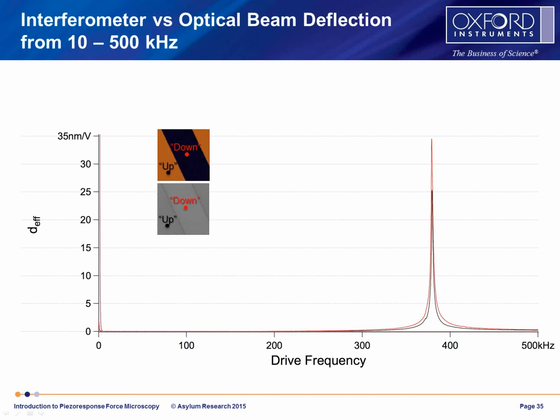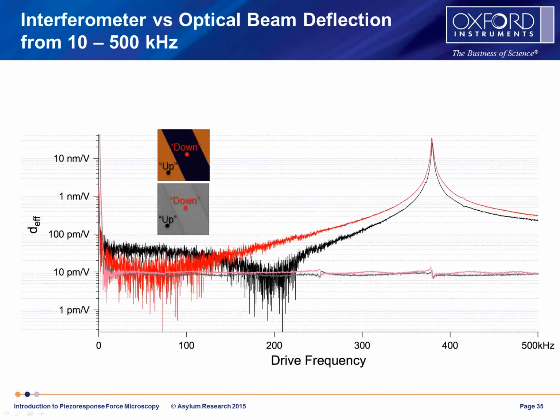So this tune here shows, again, we're revisiting the old data I showed you, the up and down domains. There's the domain images we have. These are the tunes plotted on a linear scale. You can see that there's not very much visible here because the amplitude is very small. If we take that same data and plot it on a log scale, you can see it much better. So the black and the red solid lines show the optical beam, so the normal AFM spot that most AFMs use over that range. And you can see that structure that I showed you in the very beginning of this section on quantifying it. The pink and the gray show the interferometer data over that same frequency range.